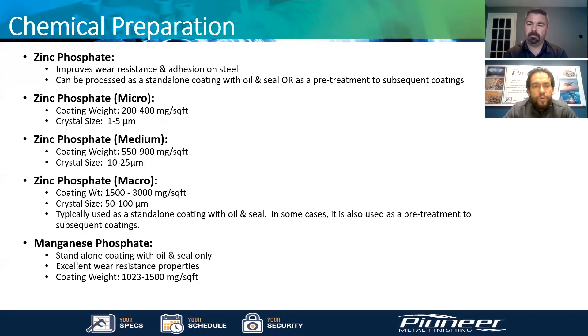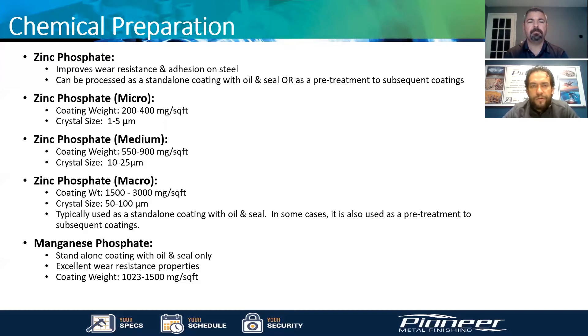We also have a medium phosphate with coating weights from 550 to 900 milligrams per square feet and a crystal size of 10 to 25 microns. This is better suited for other types of coatings — not bonding — that require a larger crystal size when you're looking to increase film thickness on the part, and it will have different properties.